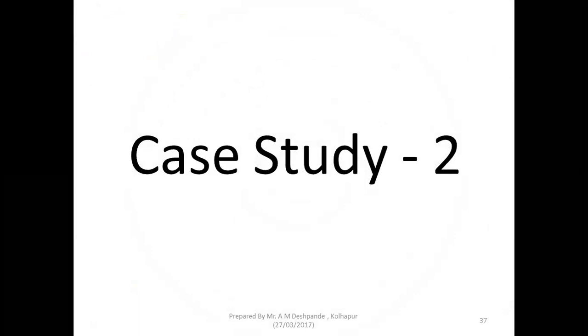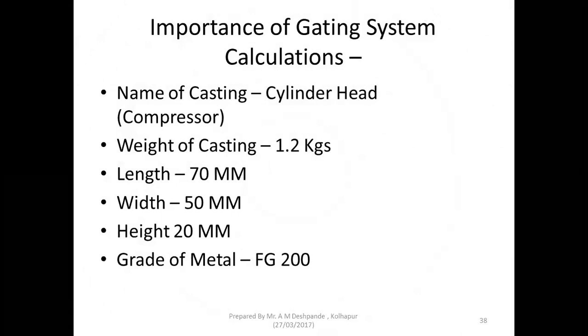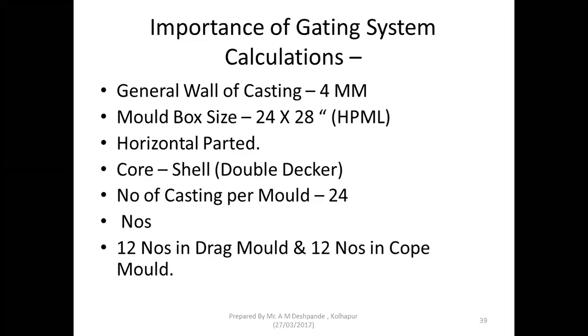This is case study 2, an interesting case study. This is a cylinder head of a compressor. Weight is just 1.2 kg. Length 70 mm, width 50 mm, height 20 mm. Grade of metal FG 200. General wall is just 4 mm. Mold box is 24 by 28. Horizontally parted, and it is double decker. Number of castings per mold is 24: 12 in drag and 12 in cope.